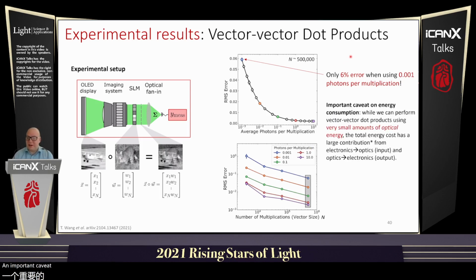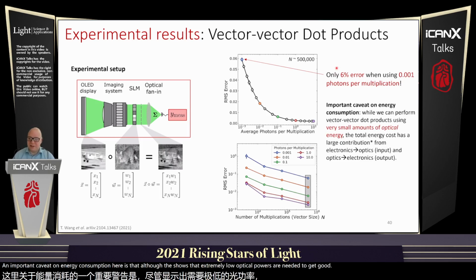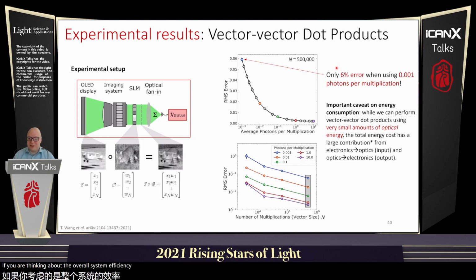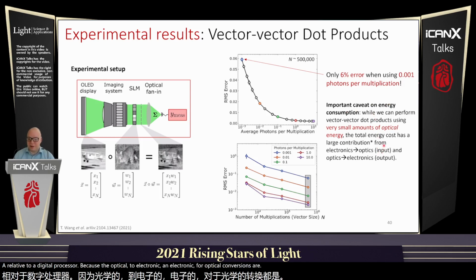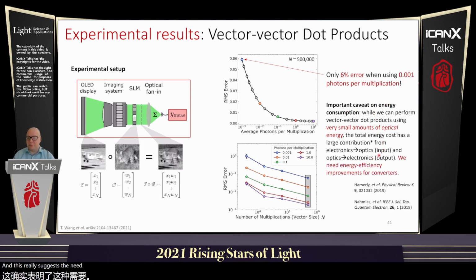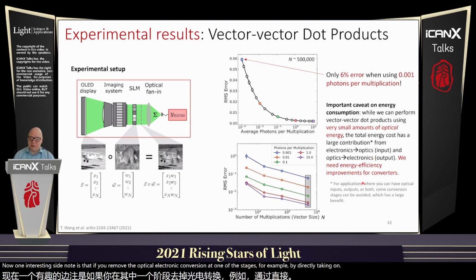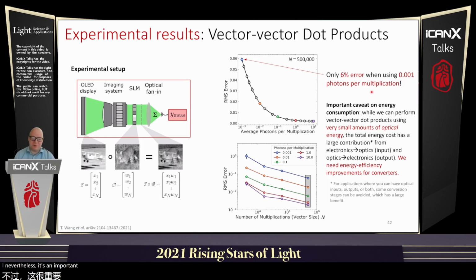An important caveat on energy consumption here is that although this shows that extremely low optical powers are needed to get good accuracy, if you're thinking about the overall system efficiency, we still use a large amount of power relative to a digital processor because the optical to electronic and electronic to optical conversions are not very efficient. And this really suggests the need to improve energy efficiency in converters. And this was a point that was also made in both of these theory papers. One interesting side note is that if you remove the optical electronic conversion at one of the stages, for example, by directly taking optical input, you can get rid of at least one of the conversion stages in the first layer of a network. But nevertheless, it's an important challenge for the field.